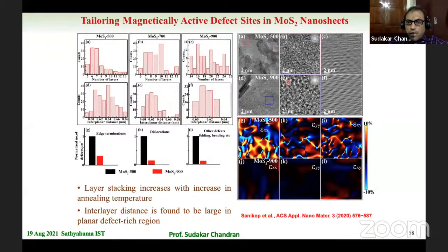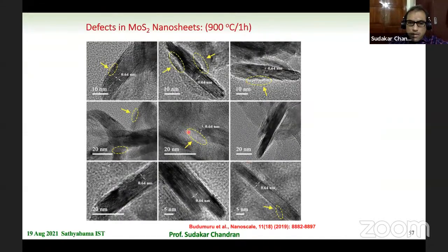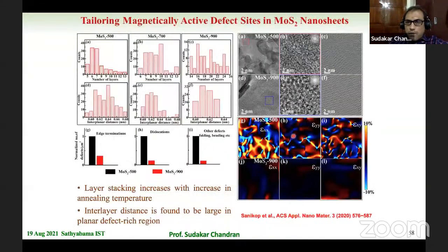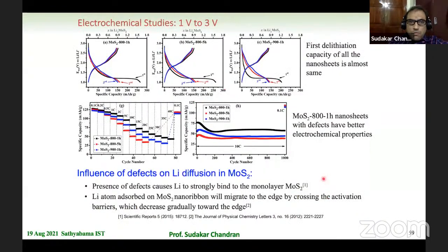Therefore, here is an example of the strain present in these layers, not in the perpendicular sheet direction, not in this plane. It's perpendicular to this that we have taken, and you can see that the strain is very much present in moly disulfide prepared at 500 degrees Celsius, whereas in 900 it's very little. So moly disulfide nanosheets with different extents of defects can be prepared.